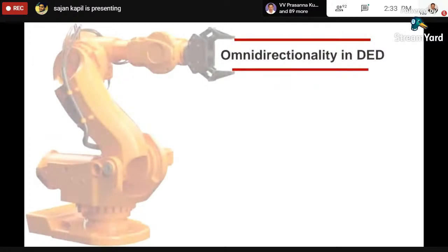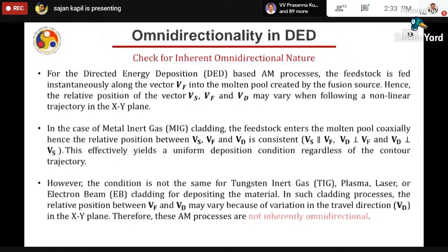So for the directed energy deposition based AM processes, the feedstock is fed instantaneously along the vector VF into the molten pool created by the fusion source. Hence, the relative position of VS, the source of fusion, that may be laser, VF, the direction of delivery of the powder, and VD, which is the direction of deposition, may vary when following a nonlinear trajectory in the XY plane. It is obvious.